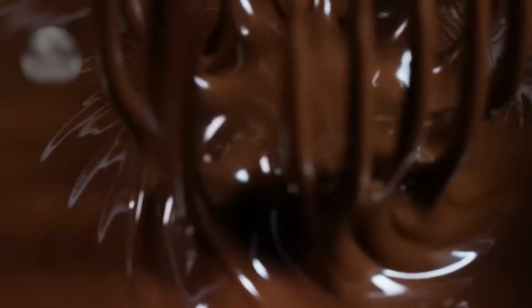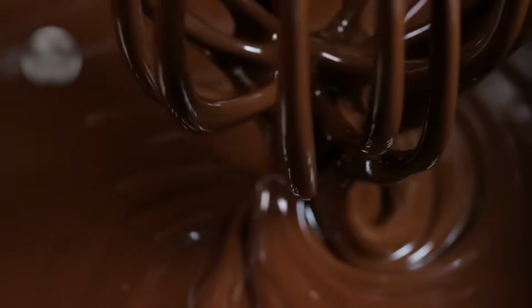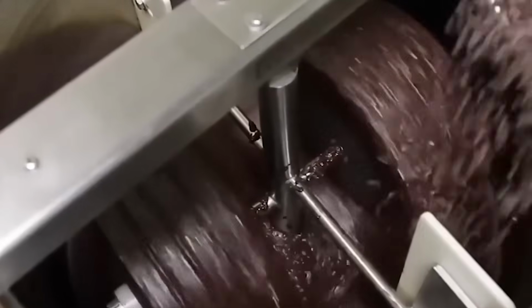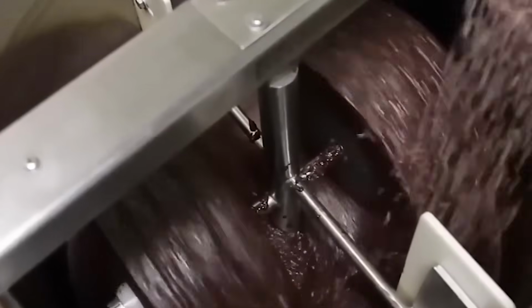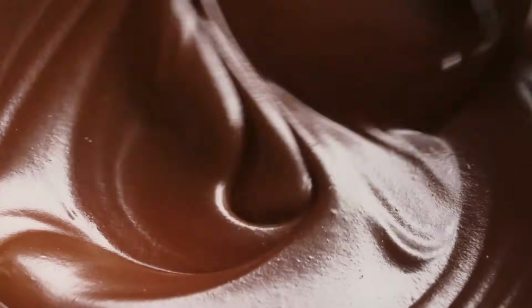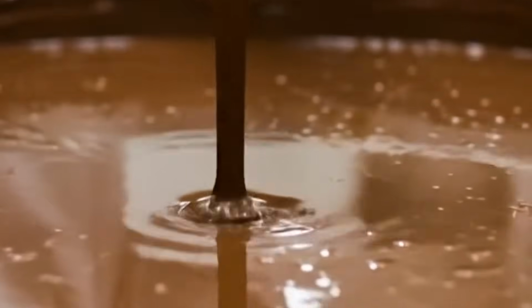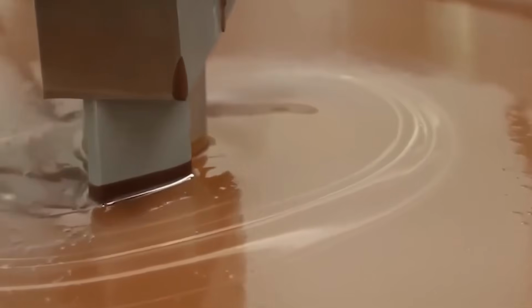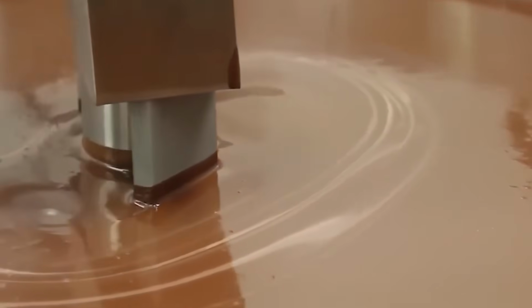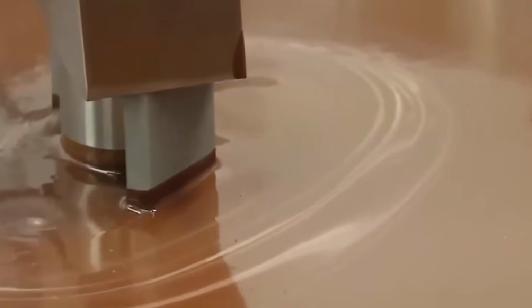Emulsifiers are typically added late in conching to fine-tune flow. Lecithin reduces yield stress by improving particle wetting. Another emulsifier can be used to reduce viscosity further. These additions allow the chocolate to flow through pumps and depositors at lower fat content or with more stable behavior. Emulsifier dosing is tightly controlled because small changes can make chocolate too thin or too thick for molding.